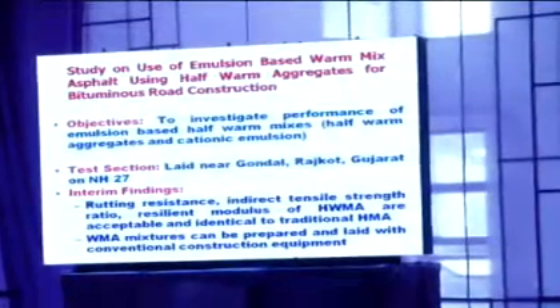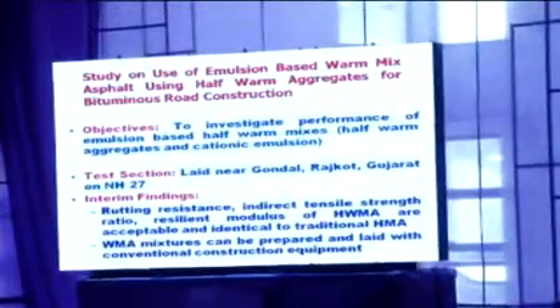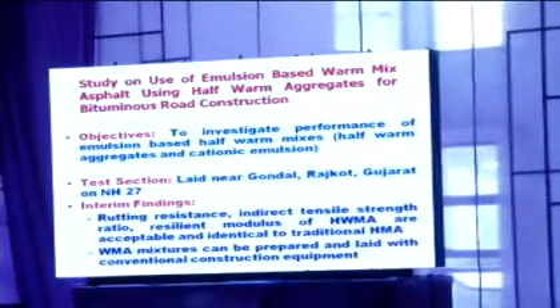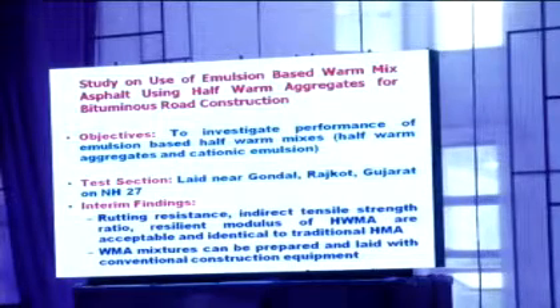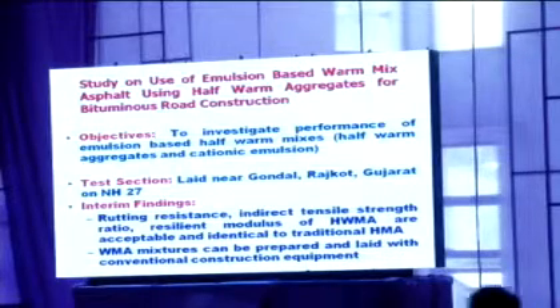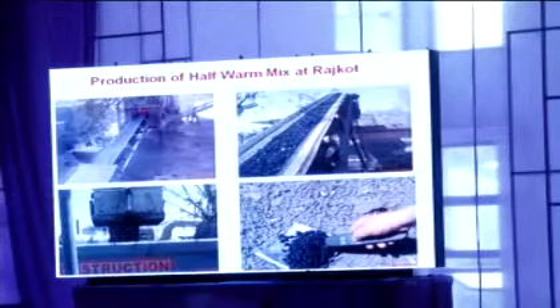Next, study on use of emulsion based warm mix asphalt using half warm aggregates for bituminous road construction. Objective of this R&D project is to investigate performance of emulsion based half warm mixes. Test sections have been laid near Gondal in Gujarat on NH 27, and it has been found out that rutting resistance, indirect tensile strength ratio, resilient modulus are acceptable and identical to traditional HMA mixes. Warm mix asphalt mixtures can be prepared and laid with conventional construction equipment.